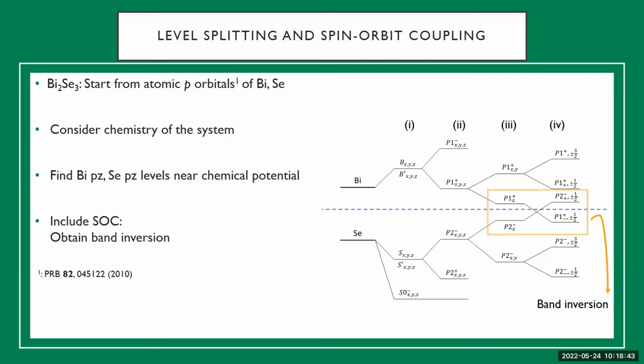material. And so the authors who came up with this model considered the chemistry of the system, meaning they considered various effects such as atomic hybridization, crystal field splitting, etc. And they found that the two levels which are closest to the chemical potential in the system are the bismuth and selenium PZ levels. So they're the Z projection of the P orbitals of these atoms. And this is like we're looking at stage 3 in the schematic figure. And then what happens is when you include spin orbit coupling in your picture, these two levels exchange positions with respect to the chemical potential.